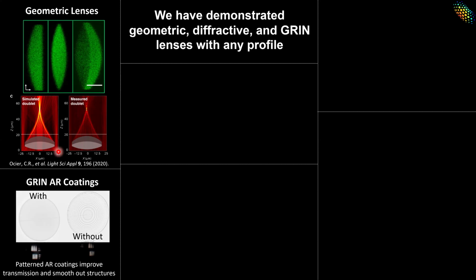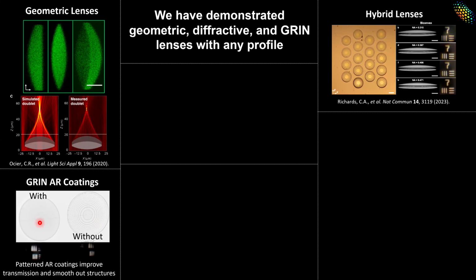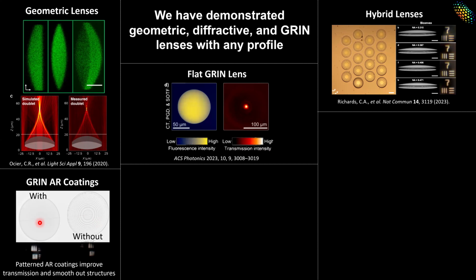And the nice thing about this is it both gives you AR properties, so you get higher throughput, and it smooths out a lot of printing defects. So we can actually print at relatively more coarse resolution than maybe with Nanoscribe or more traditional two-photon polymerization, and still get a very, very optically smooth structure. We've made hybrid lenses where you can combine refractive and diffractive structures, taking advantage of the opposite signs of their dispersion for chromatic aberration correction.